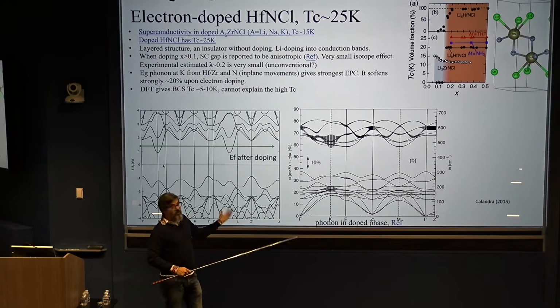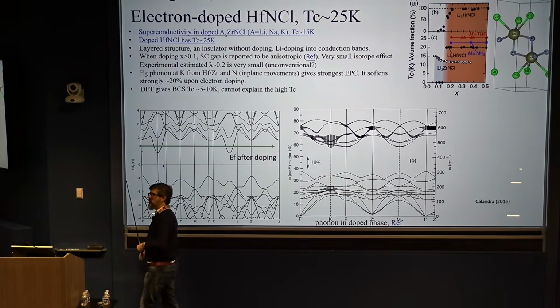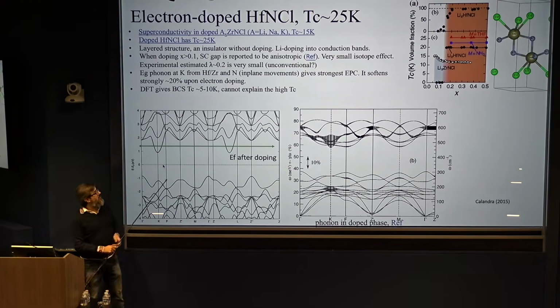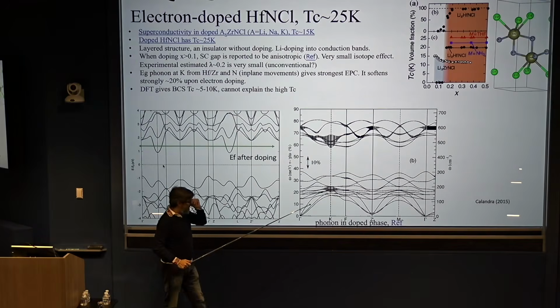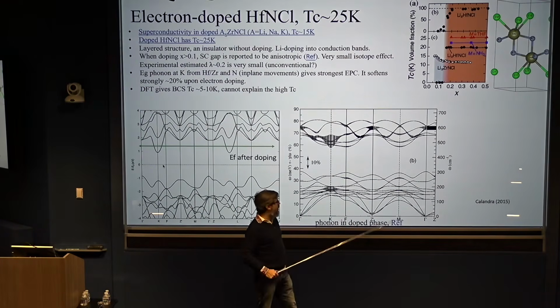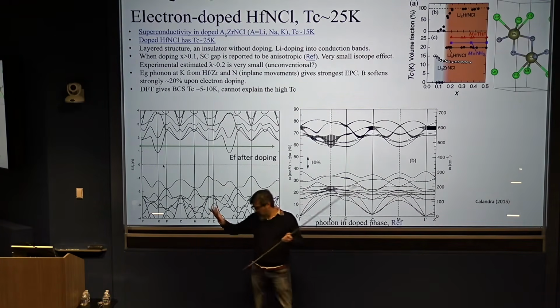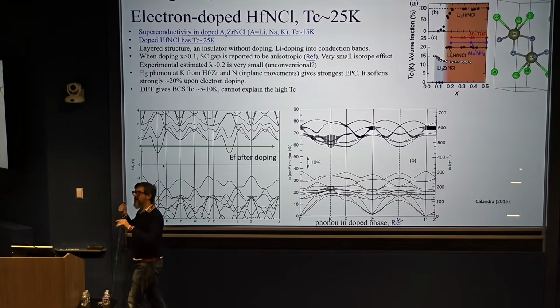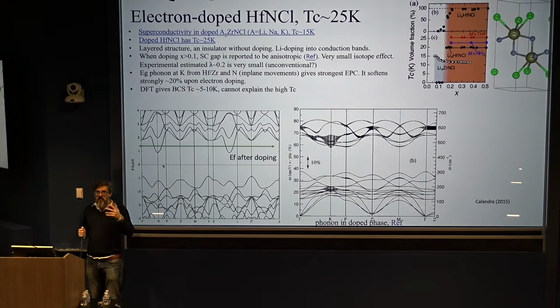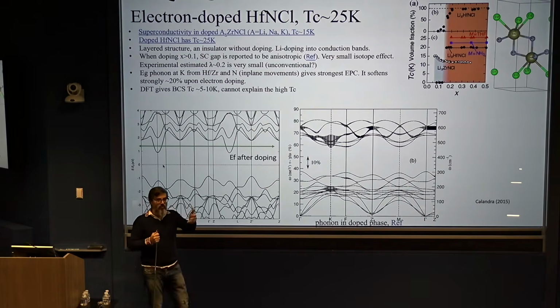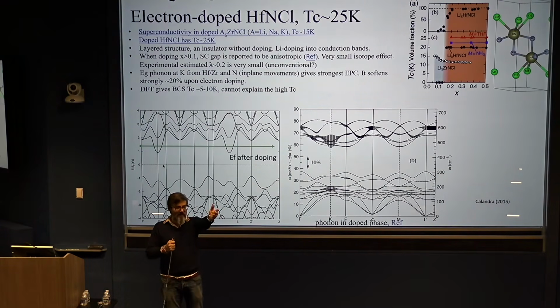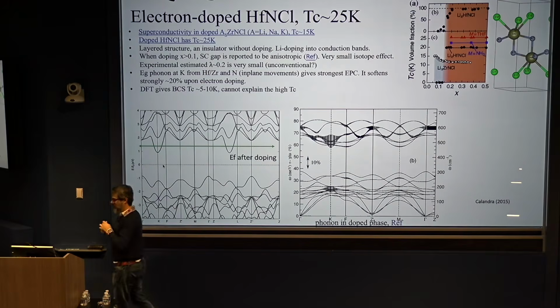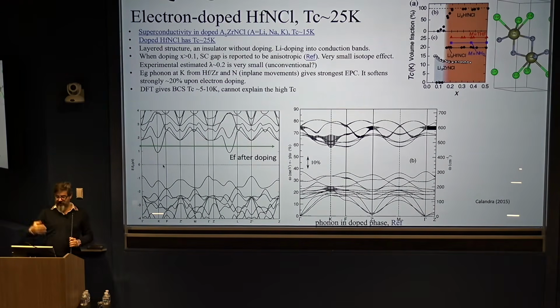If you just do electron phonon, you do get a completely mismatching TC. There are papers in the literature that say it's not electron phonon. There are papers in the literature, which Jon pointed out yesterday also, that do get the correct TC with some RPA. But what I'd like to understand is some rule of thumb. The reason why I liked Oscar's presentation yesterday is that it's a rule of thumb: if the mass is large, then I'm going to get this logarithm, and I can evaluate at least ratios of different temperatures based on the mass.